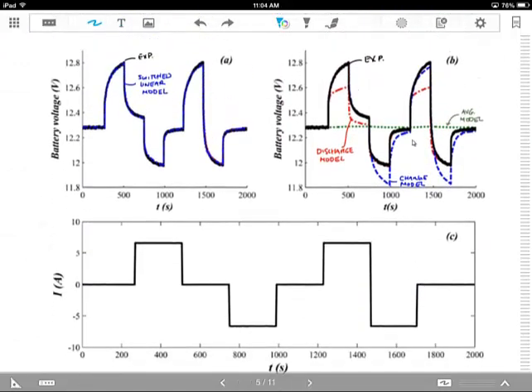So if you put it all together and just look at what happens when you charge and discharge an actual lead acid battery, this is some experimental data. The black curve is experimental. The blue dashed line is our switched linear model. So you can see here again, it was at rest, and we do positive charge, discharge, charge, discharge, and rest over 2,000 seconds. So this is what the pulse profile looks like.